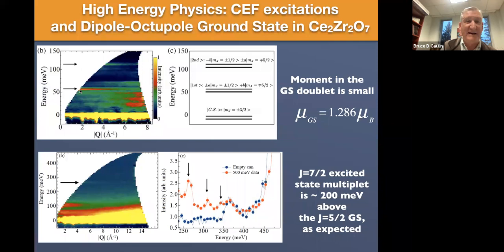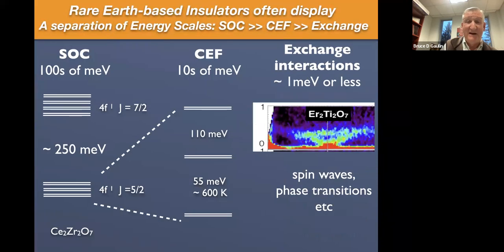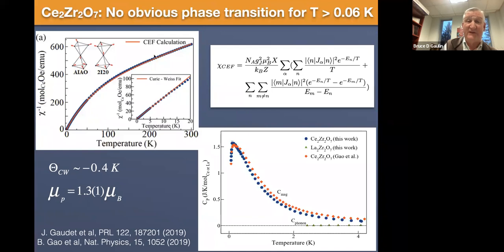Actually, this is an eigenvalue problem. And just by looking at the data, you can read off the eigenvalues. The eigenvalues are the energies of the transitions, so they're the splittings between these doublets. You can just read those off. So the eigenvalues you almost get for free. And then the eigenvectors are the wave functions that describe these pseudospin 1/2 degrees of freedom. And these you get with a combination of looking at the relative intensities between the transition from the ground state to the first excited state and the transition from the ground state to the second excited state, along with a fit to the Van Vleck susceptibility here, because this depends on knowing the crystal field states as well.